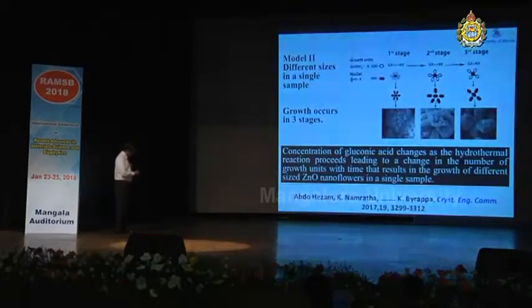And in model 2, the other model, we have described the same formation with 3 stages, again with the same growth units, and these are the different morphologies with time and concentration of gluconic acid as it changes under hydrothermal conditions. It leads to a change in the number of growth units. These are the growth units. The number changes with time, which results in the growth of different sized zinc oxide nanoflowers in a single sample.